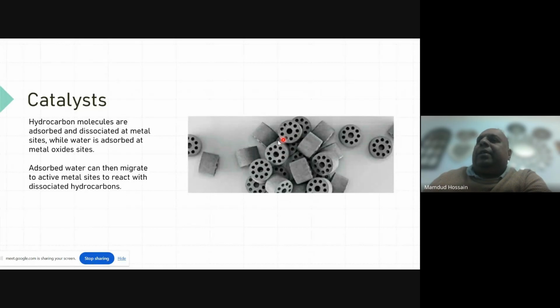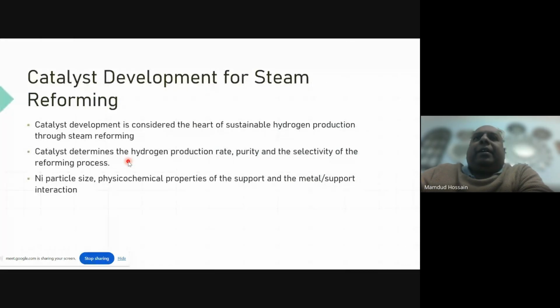These are alumina or aluminum oxide tube kind of thing, a pellet kind of thing with a number of holes, and you put nickel on top of that, and that catalyst actually enhances your chemical reaction because it allows hydrocarbon molecules to be adsorbed and dissociate at the metal site here, nickel site, and also allows water to be adsorbed on the metal oxide site. Once adsorbed, it does a surface chemical reaction, migrates, and breaks up the hydrocarbon. So steam and hydrocarbon are actually adsorbed on the surface of this catalyst, and then the chemical reaction takes place, and that's the role of the catalyst.